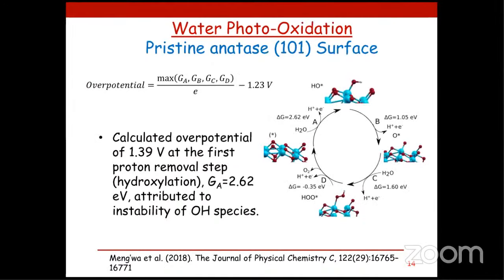Okay, Prof. So this is a photooxidation reaction whereby we have hydroxylation, dehydrogenation, then formation of hydroxyl species, then formation of the oxygen. So we have A, B, C, and D. Now, if you do the photooxidation reaction, the overpotential is calculated from getting the maximum of the Gibbs free energy of the reactions just mentioned, A, B, C, and D, minus 1.23, which is actually the equilibrium potential.